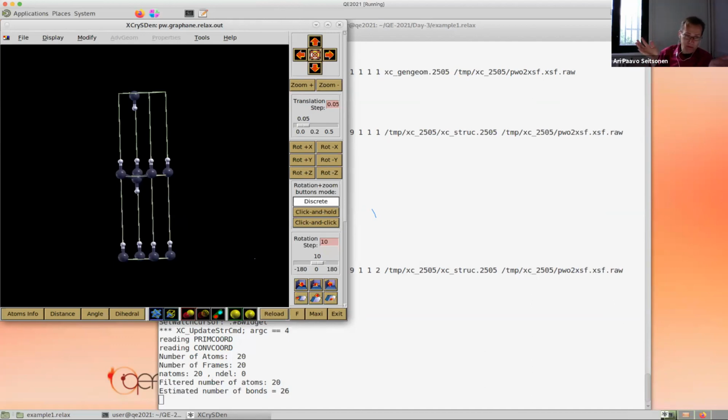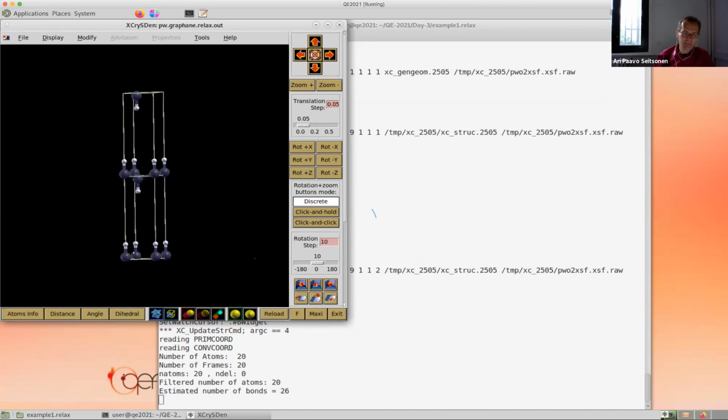Everything depends on your system. For example, some people have studied the adsorption of ions on graphene. It's a very ionized atom, so it creates a strong dipole if it's only above the plane. So then you probably need much more space also. It depends really on your system, how you localize the electrons and so on. So here, initially, you can have a look and get an idea how close the atoms are. I will not give any value. You always have to think what is enough for your system, so you can do the convergence check.